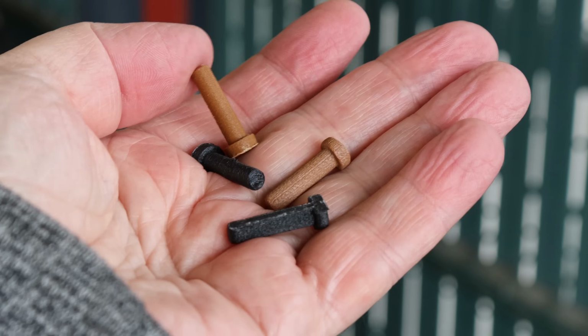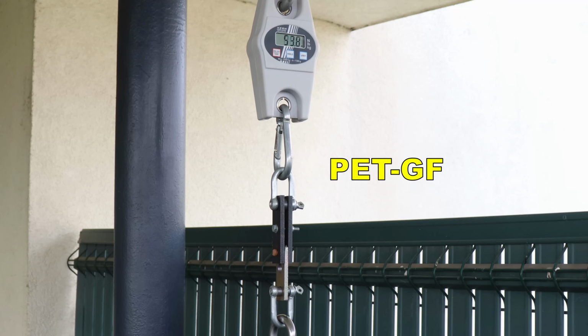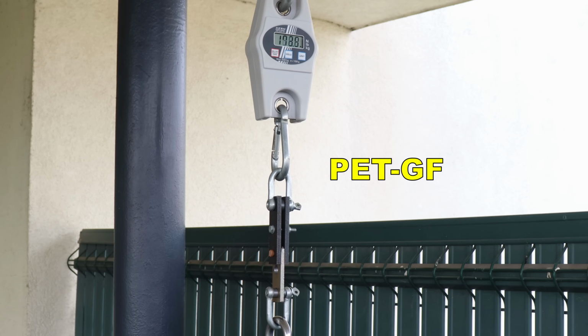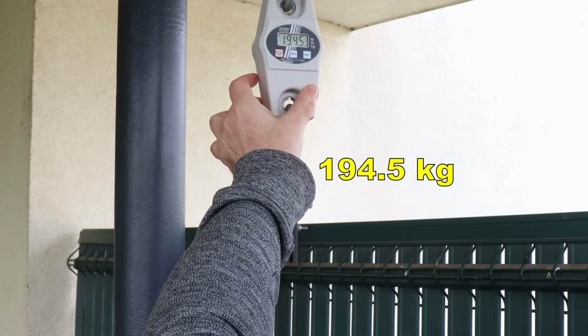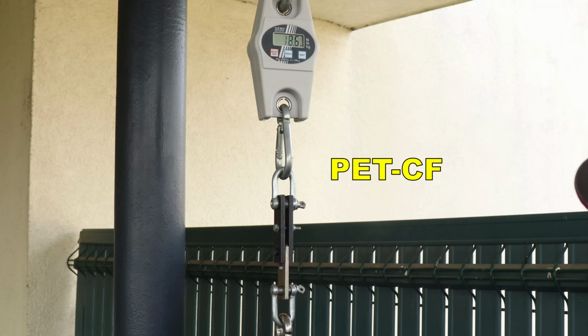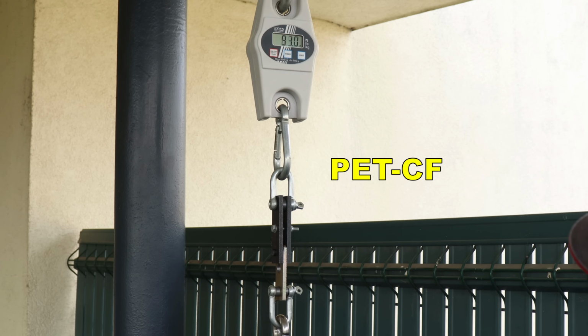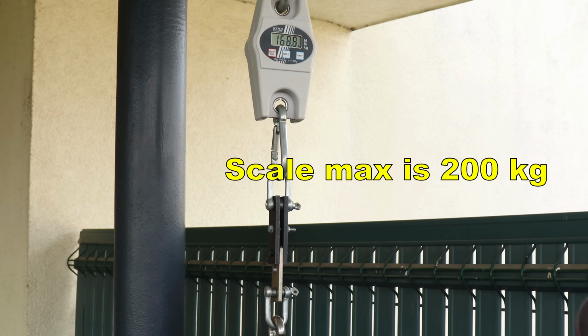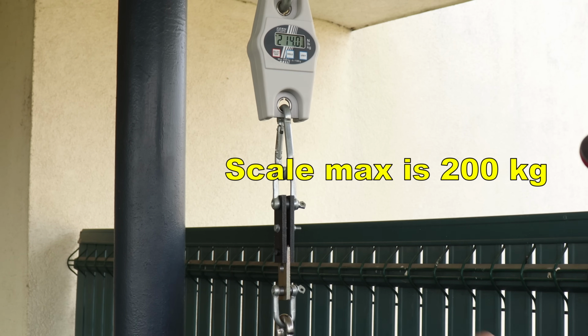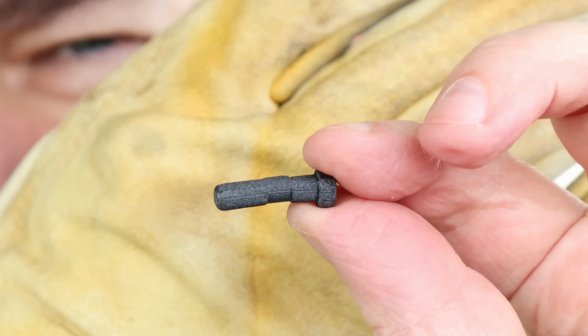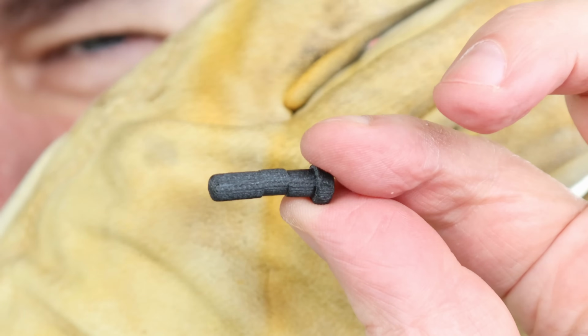And now the shear stress with horizontally and vertically printed test objects. I'm starting with the horizontal ones. And here I know that I will have a problem with the carbon fiber version because it is usually stronger. And the maximum of this hanging scale is 200 kg, so I have to stop earlier. And this is the deformation after this attempt.